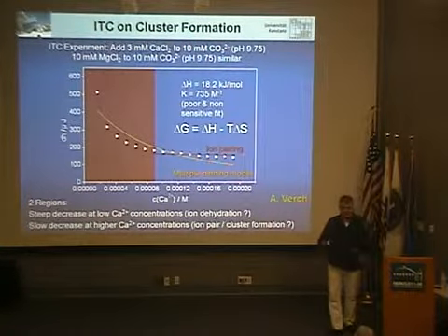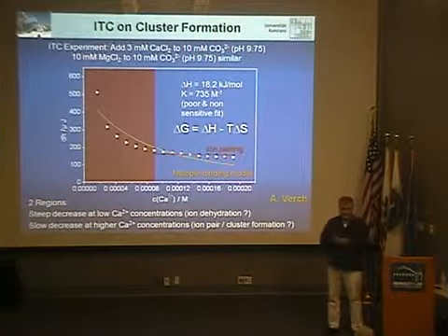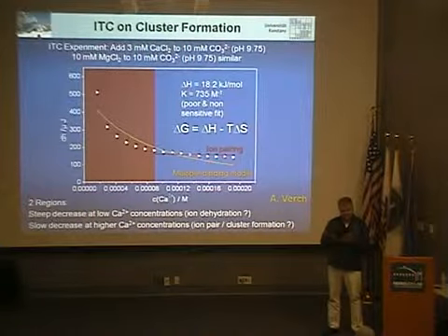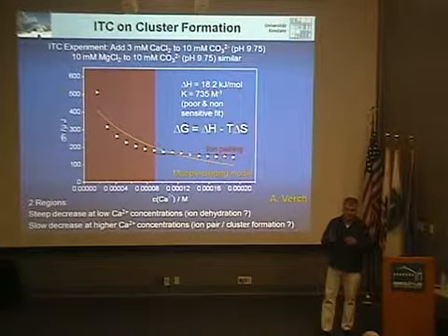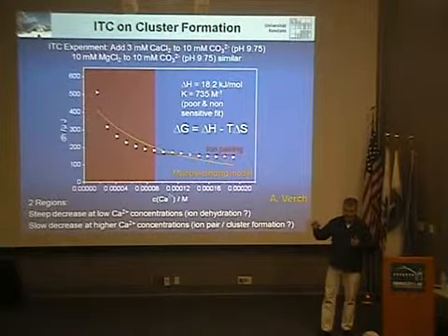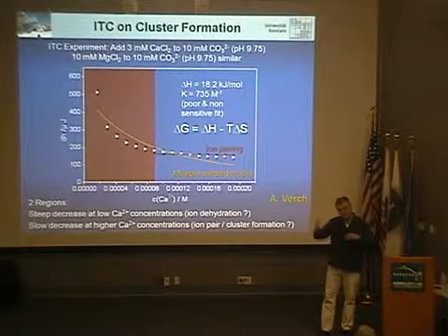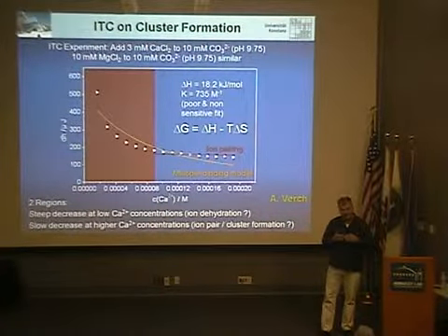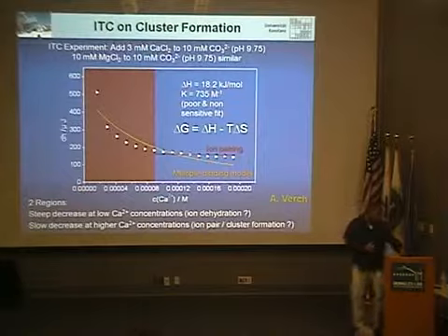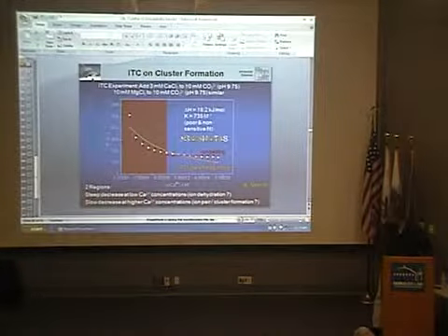Well, that's certainly the point, that magnesium is much harder to dehydrate. And that was also something we had in mind when we designed these experiments. We thought maybe magnesium is so difficult to dehydrate that calcium is so much more favored over the magnesium. But in the end, if you look at the curves, the difference is not that high. So it was up to a factor of 4 only, if I remember.